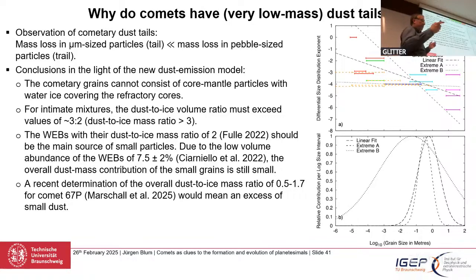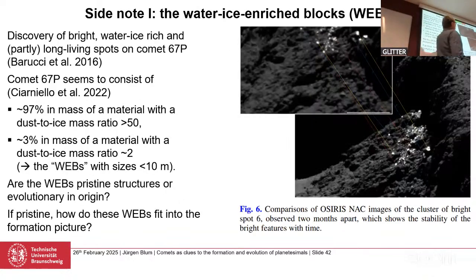So 3:2 dust to ice volume or 3:1 dust to ice mass ratio at least. Most of Comet 67P at least seems to have a dust to ice ratio in excess of 2 or 3. But there are a few points called the WEBs, water-enriched blocks, which seem to have a dust to ice ratio of 2, which is below that, but a few percent is fine. That is the dust that goes into the tail. And here you see the white spots that partly even survived over weeks or even months, identified in Comet 67P, long-living, bright in color, so ice-rich, water-enriched blocks. And I interpret them as the sources of the dust in the tail. And the rest of the comet, which is most of the surface and most of the volume, is completely inactive in terms of providing dust to the dust tail.